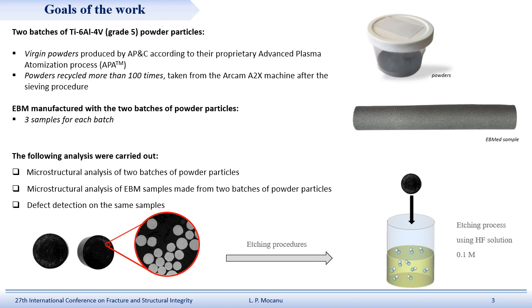So, more in detail, in this work we analyzed two batches of titanium powder particles, grade 5. The first one is a batch of virgin powder produced with a plasma atomization process, while the second batch is a powder recycled more than 100 times. And then, manufactured with these two batches of titanium powder particles, we have 3 samples for each batch, so a total of 6 samples, in order to carry out the microstructure analysis on the two batches of titanium powder particles. And then, regarding the samples, we perform both the microstructural and the internal defects analysis.